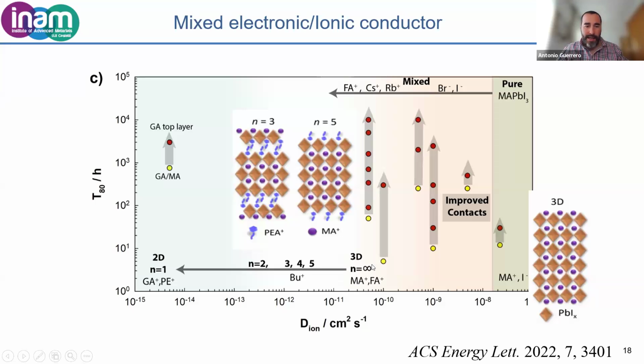Okay, and as you see here, when we reduce the dimensionality of the perovskite, the T80 of the device increases a lot, and then we can get up to 1,000 hours of T80. So there's a relationship between the stability of the device and the supply of ions to the contacts.